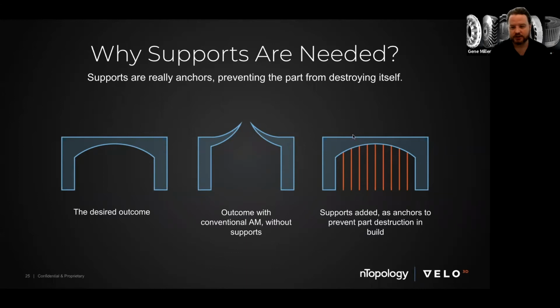So the conventional solution is to add supports to these low overhangs. That's what we're showing here in red. These are support material that's added to the part. And that's fine if you can access that material and remove it after you're done printing. In this case, we have some really isolated volumes which are inaccessible after printing, and you just can't get in there to remove any of the support. So we can't put it there, but the good news is we don't have to.